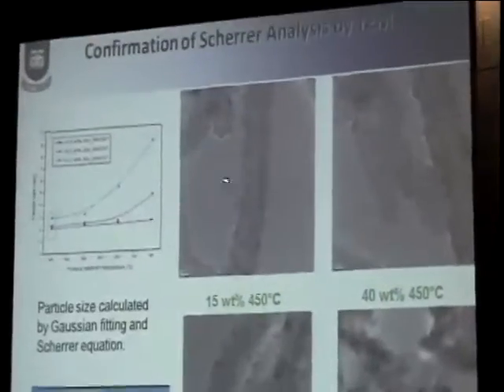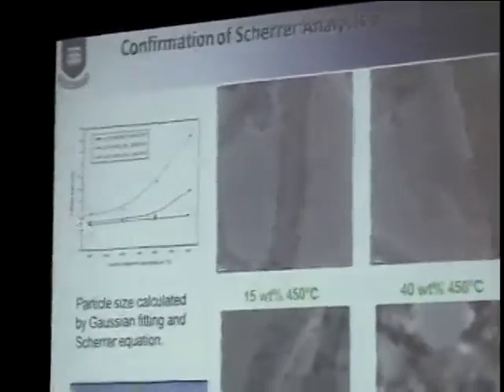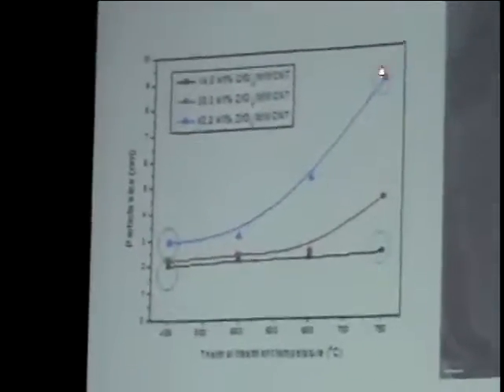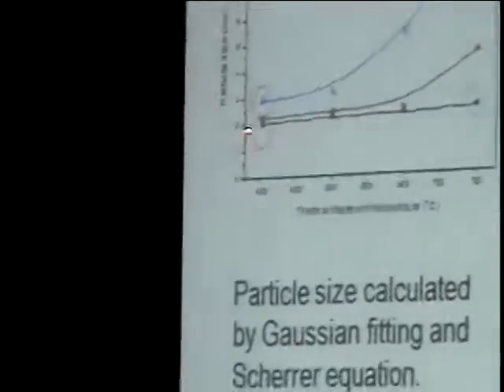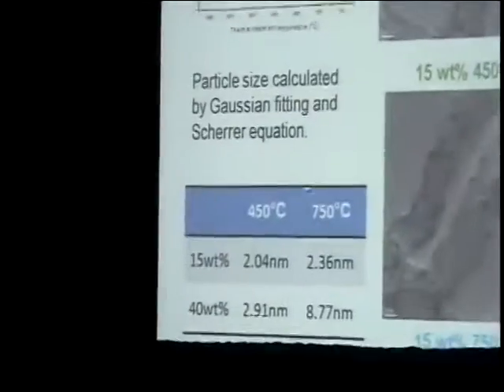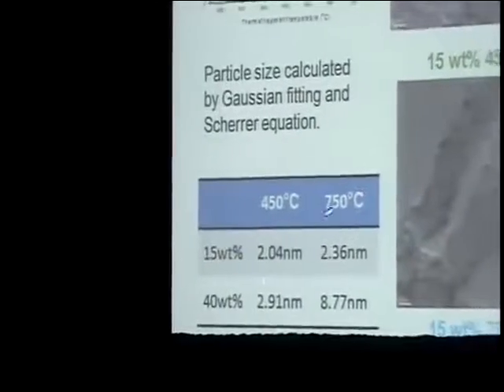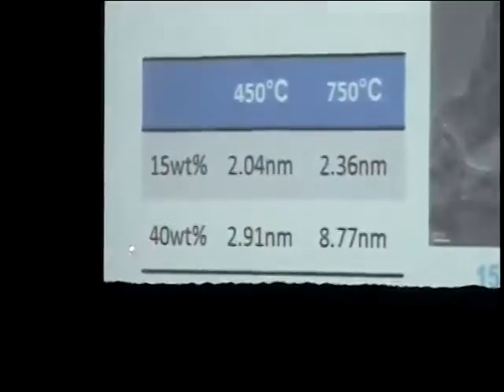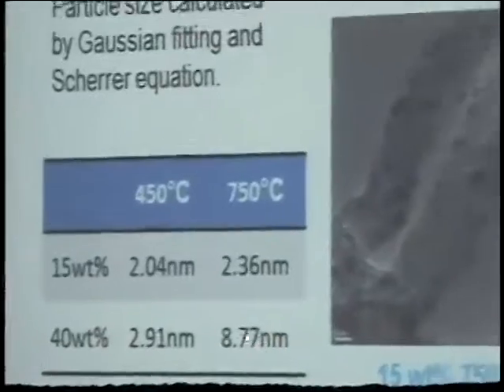And here we're going to look at them by Scherrer analysis of X-ray diffraction. This is too small for you to truly read, but with 15% weight loading, they start out at 2 nanometers, and after being heated to 750, they remain that. At about 40-some weight percent, they're more like 3 nanometers, and after 750, they're up to about 10 nanometers. So that's summarized as stable at 450 and 750, stable at 15 weight percent, and unstable towards sintering for 40 weight percent.